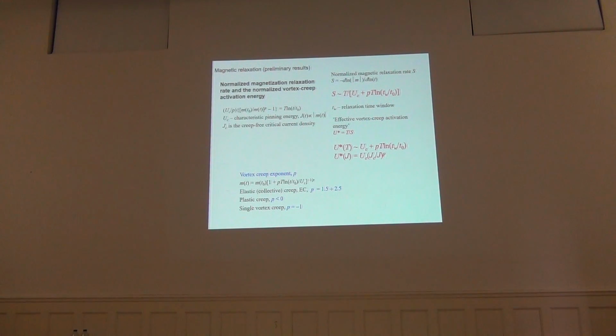Now, we also started to do some preliminary magnetic relaxation measurements. So again, we use the normalized magnetic relaxation rate and the normalized vortex creep activation energy. So we have a characteristic pinning energy, in which, of course, the width of the magnetization loop as a function of time is proportional to the current density as a function of time. And in the following formula, JC is the creep-free critical current density. So the normalized magnetic relaxation rate, which we also saw in the previous talk, but in that case it was about the strong pinning centers only, is given by this formula, in which we have a relaxation time window.